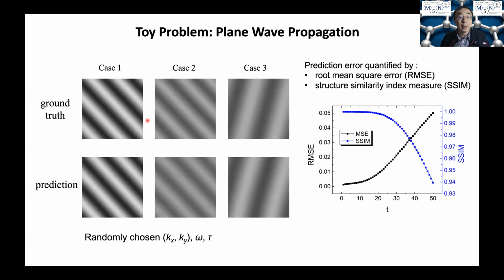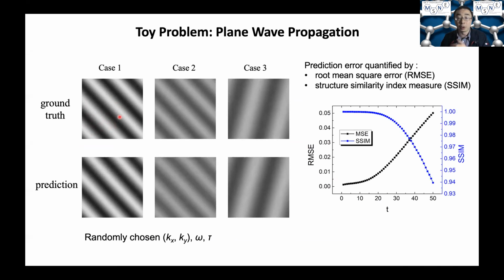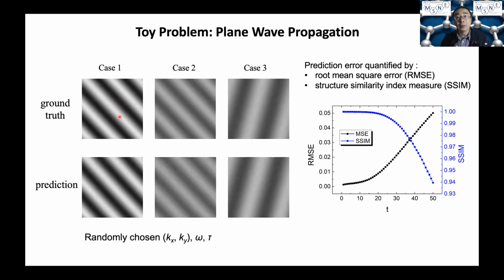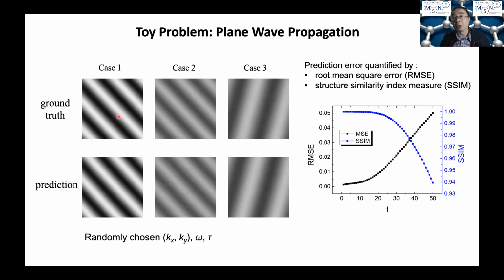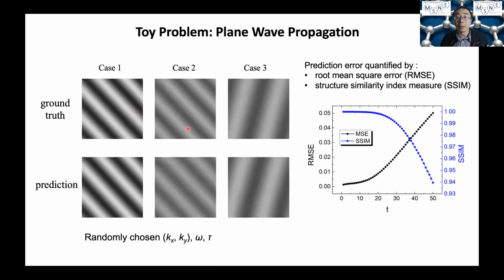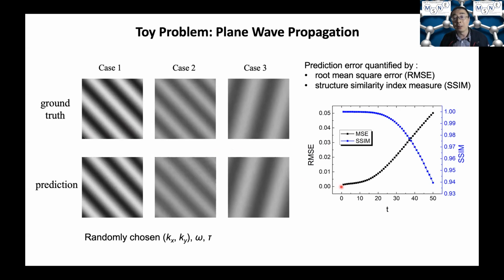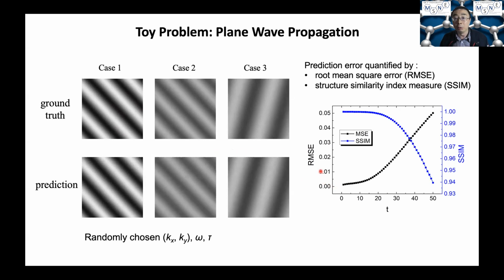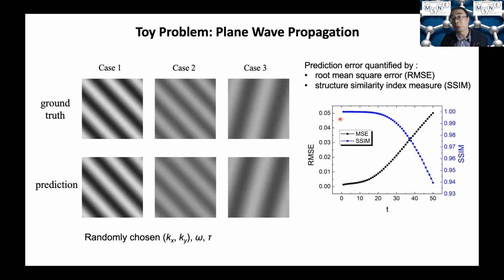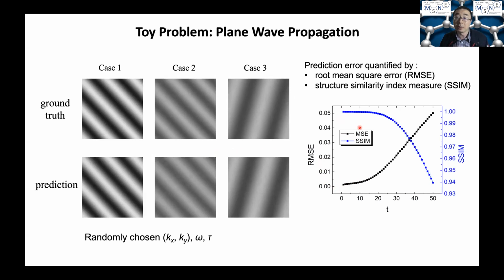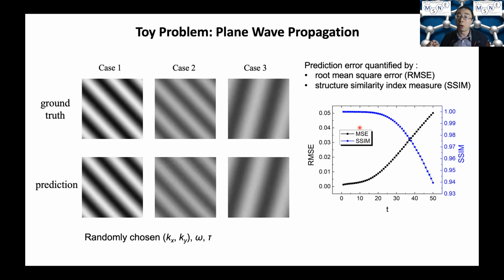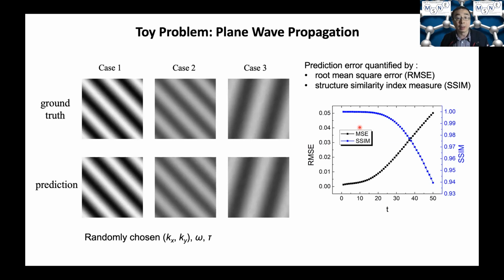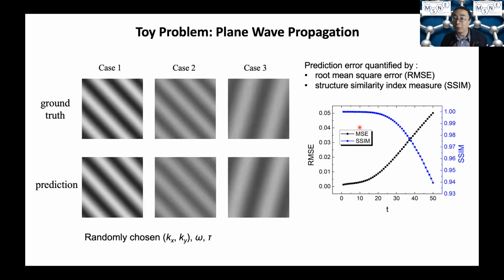We found that when you use wave parameters such as the wave vectors, wave frequency, and the damping coefficient, which are not included in the training data sets, the trained model is still able to accurately predict the wave propagation dynamics. In terms of the pixel-wise comparison, the root mean square error between the ground truth and the predicted images is below 5% over the prediction duration. Another measure, called the structural similarity index measure, is above 94%. Here SSIM equal to 1 means two images are identical to each other. So the overall accuracy of the prediction made by the RNN is very nice.